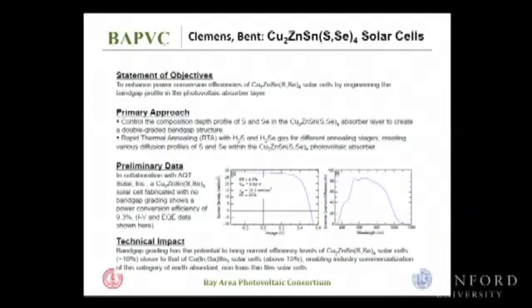So we are looking at silicon, we are looking at III-V, we are looking at different absorbers. Another example is Professor Bruce Clemens and Stacey Bent, who try to develop CZTS solar cells. We know CIGS solar cells have about 20% efficiency. It's a thin film solar cell, but indium is high cost, not an abundant element. This research from multiple research groups tries to replace indium with zinc and tin. Zinc is divalent, tin is tetravalent, and indium is trivalent. Try to use two elements together to have the effect of indium.